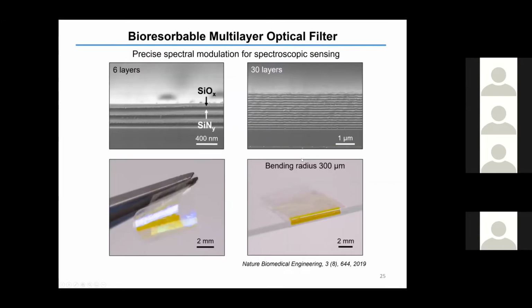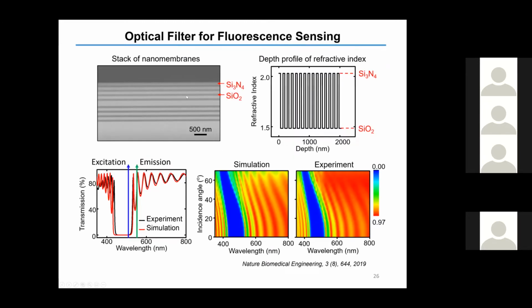The third type of bioresorbable spectroscopic sensing system is based on an optical filter made of multi-stacks of alternating layers of silicon oxide and silicon nitride supported on PLGA biopolymer films. The whole system is bioresorbable and mechanically flexible, even for the 30-layer films, with a minimum bending radius around 300 micrometers. By controlling the periodicity or a combination of periodicity, we can modulate the transmission spectrum through the optical filter in a designed manner.